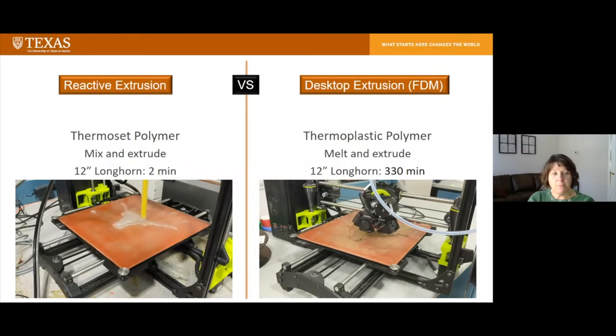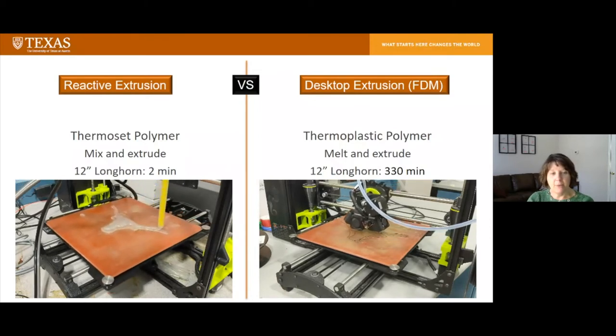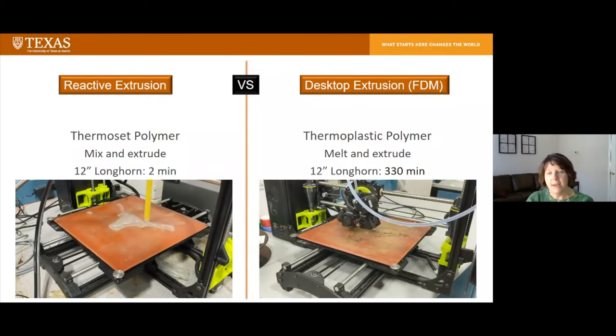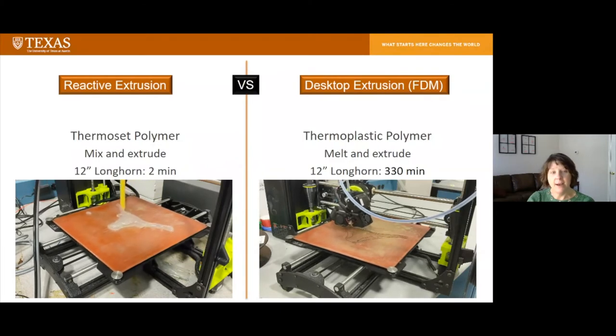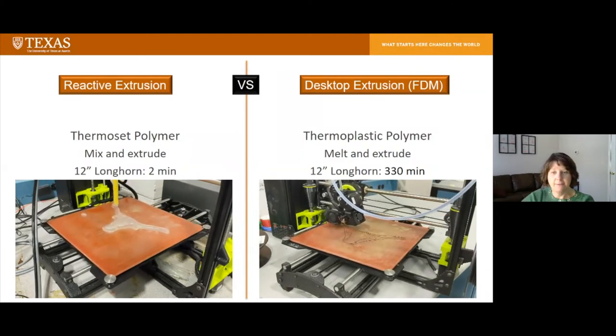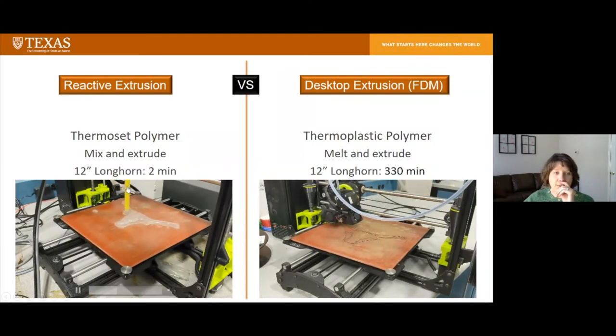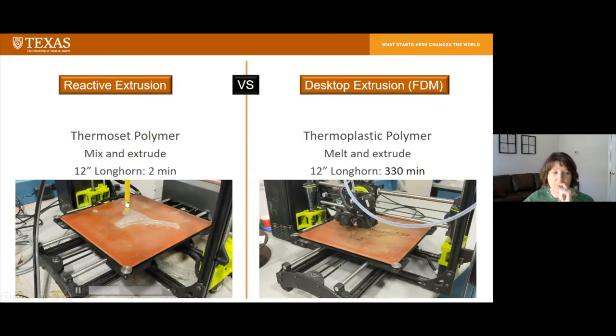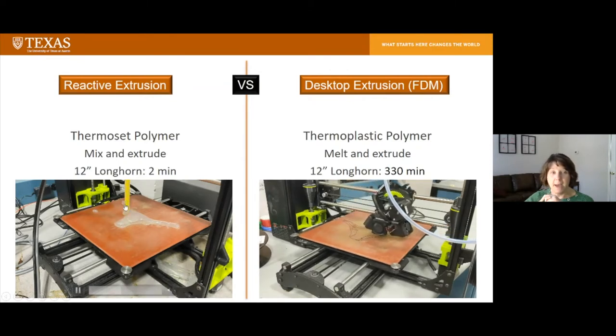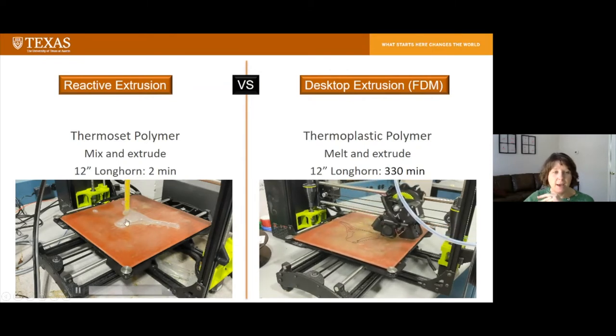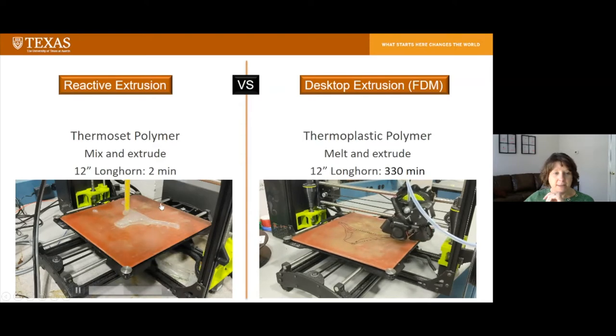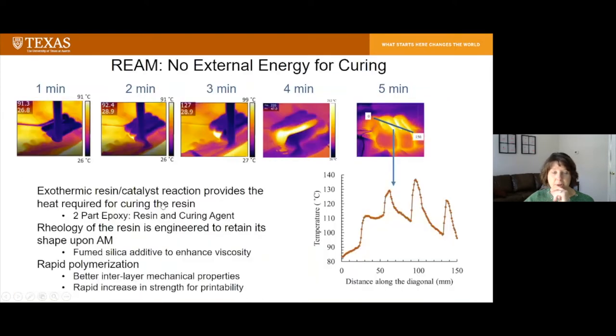So what prints in about 2 minutes in our reactive extrusion printer takes about 5 hours in the plastic printer on the right. And one of the things you'll notice from this video is the yellow nozzle is the mixing nozzle. So the two-part epoxy is being mixed in that mixing nozzle passively as it passes through, so that it's mixed by the time it's deposited. Then it rapidly cures, right? So there's no external energy required for curing these materials.